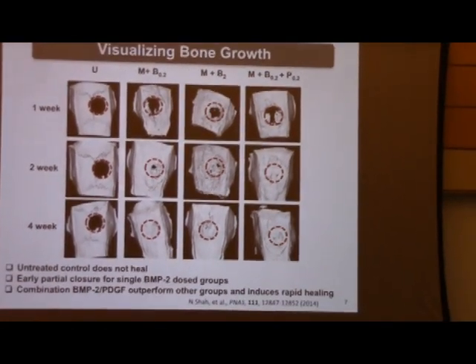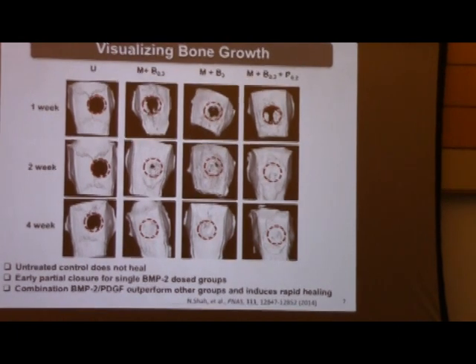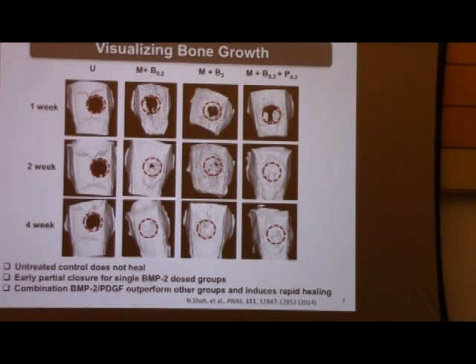So when Shah did this study, there are a couple of ways in which we can look at what's happening. We use a cranial defect model in which we generate a defect in the skull of a rat, and we use a control to show that this defect cannot close over time. We then use micro CT. So here you're looking essentially at a kind of X-ray of these defects over time to see the fill-in of bone in the matrix.